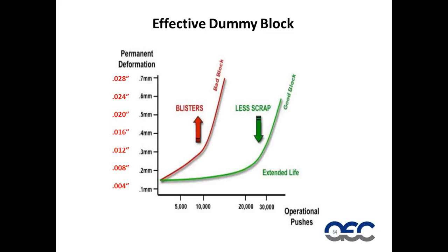So if a dummy block started at maybe 8.360, and after you use it for a day, it's 8.370, we've seen about 10 thou deformation. If we see 20 thousandths of an inch deformation, so the original size is increased by 20 thou, we're going to start prematurely sealing, we're going to start interfering with that aluminum that we left on the ID of the liner, and we're going to see an increase in blisters and our surface finish decrease.